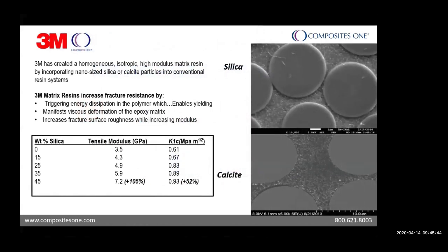And the last one that we see is relevant out there are the 3M nanosilica or nanocalcite products. I show a couple SEM images so you can see how well dispersed it is in the resin matrix for both the silica and the calcite. The nice thing here, it's a pre-blended resin system, so the customer doesn't have to worry about shear mixing. It's already pre-blended. And we see good improvements in both tensile modulus and toughness as well.